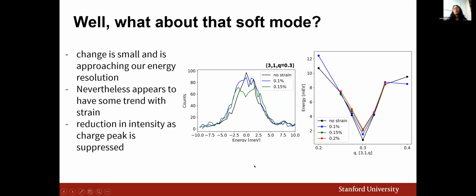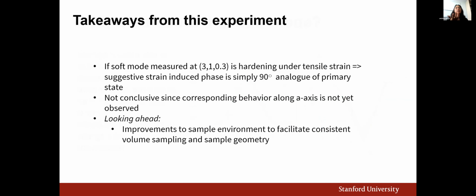So we can fit this to a series of modes, and we see that indeed there appears to be some hardening of the phonon mode at the CDW wave vector. So we were very excited to see some change in the data as we apply strain and affect the CDW in this material. All right, so this seems to suggest that if the soft mode that we're measuring is indeed hardening as we apply tensile strain, the rotated CDW phase sort of seems to be behaving just as a 90-degree analog of the primary state, the unrotated CDW wave vector.